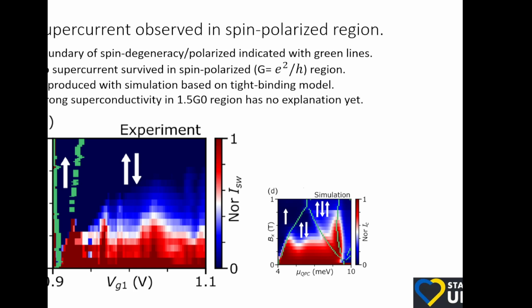Because as Cooper pairs try to enter the wire, there is nothing at the interface. It's so pristine, nothing to cause the spin to flip. So what we actually need to do is put some garbage at the interface. Ideally, unpaired spins, some oxide or something like this, to allow spins to flip, and then flip back, and then maybe we will see it.